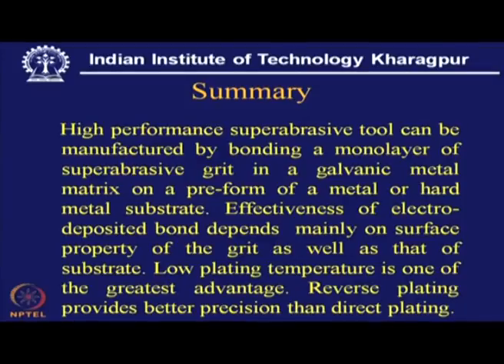High performance super abrasive tool can be manufactured by bonding a monolayer of super abrasive grit in a galvanic metal matrix on a preform of a metal or hard metal substrate. Effectiveness of electrodeposited bond depends mainly on the surface property of the grit as well as that of the substrate. Low plating temperature is one of the greatest advantages of this process, and reverse plating provides better precision than direct or positive plating.